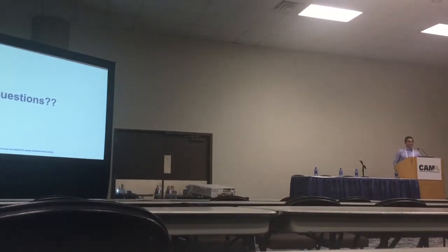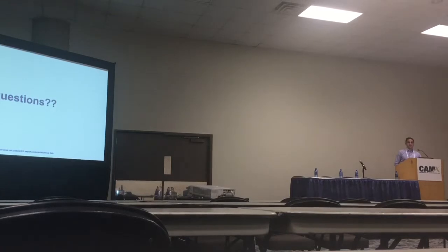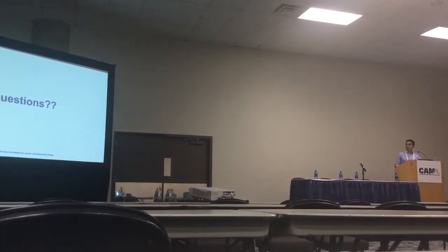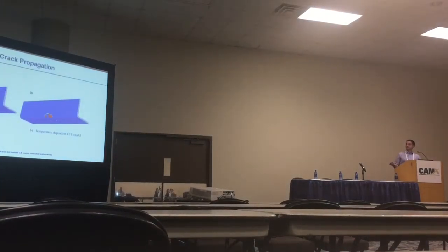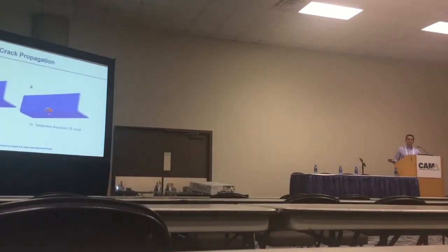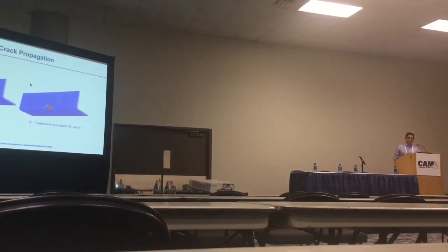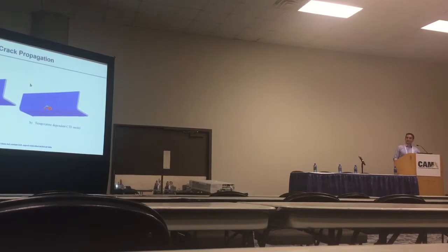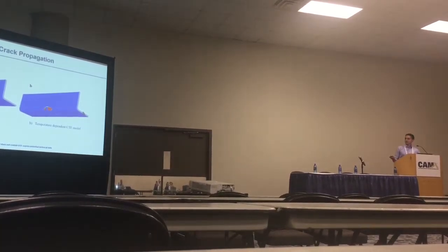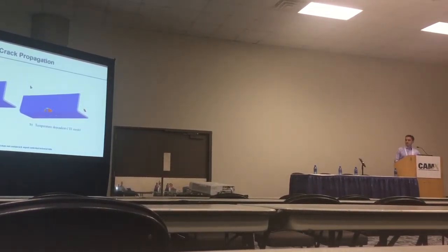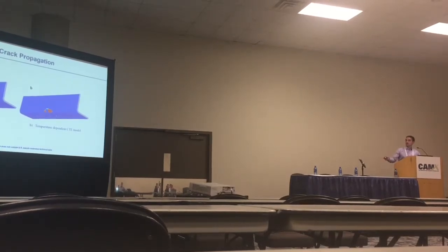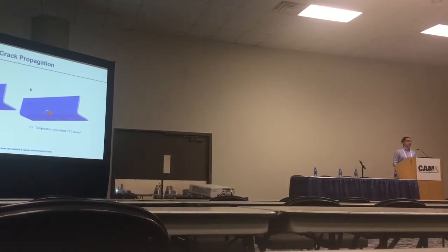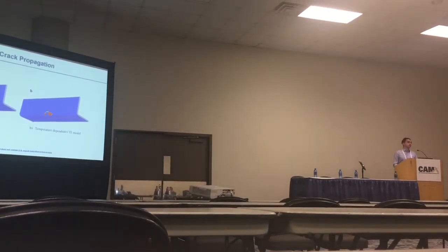Yeah, we actually have done testing. I don't show it here. We have done quite a bit of testing, specifically on correlating the crack propagation as well as the first node release. And I would say we're within 30%. 30% of what, essentially, is the length of the crack that you're seeing, predicting the length of the crack right here, how wide it grows through NDI, as well as the load at which the crack initiates.